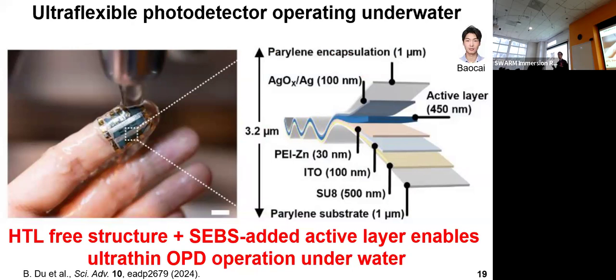Because the organic photodetectors have almost the same structure as organic photovoltaics, we could fabricate both solar cells and photodetectors with the same processes. And in this study, we added elastomers, more specifically SEBS, into the active layer material to make adhesive, sticky interfaces between the active layer and the bottom and top interface layers, to make the photodetector systems more water robust.